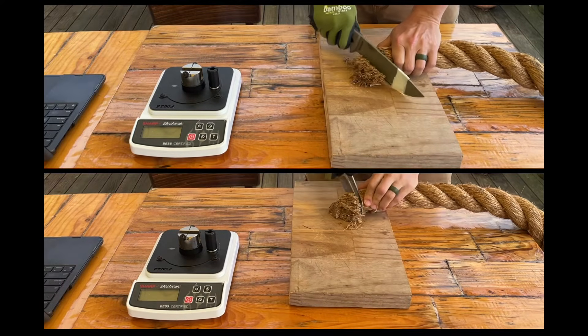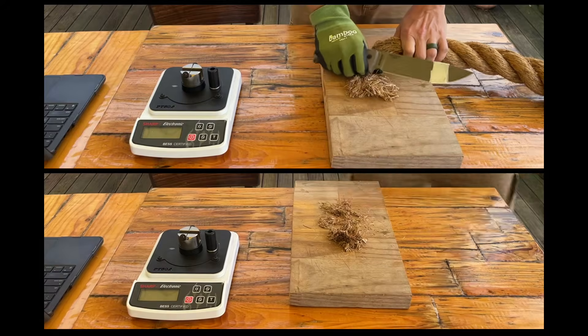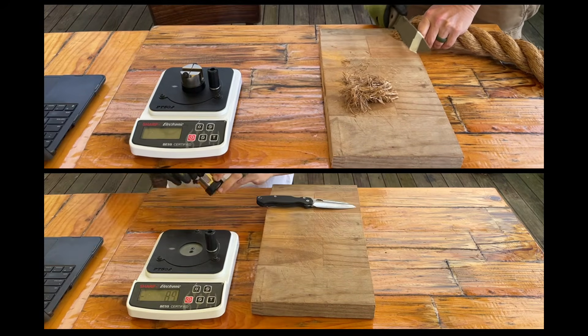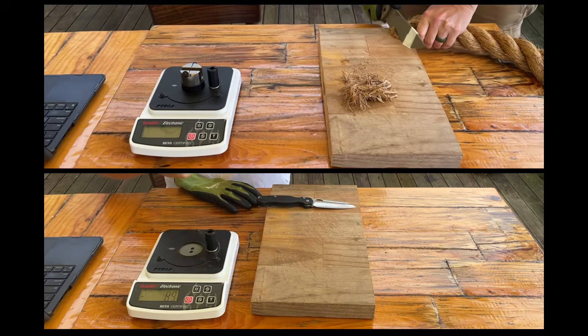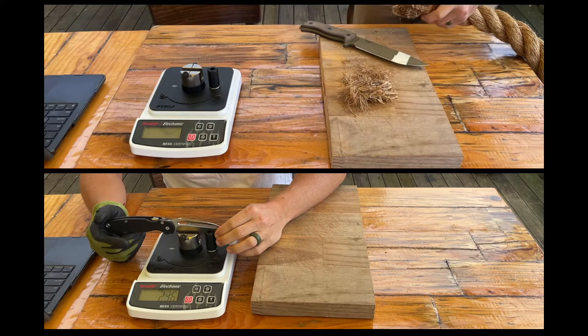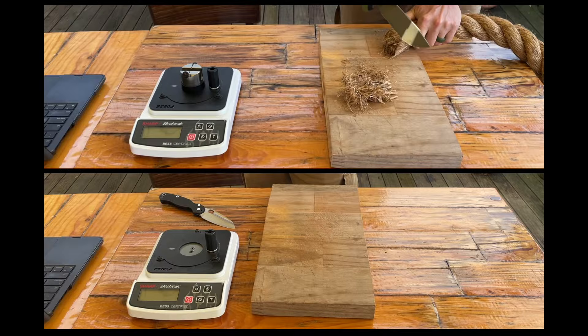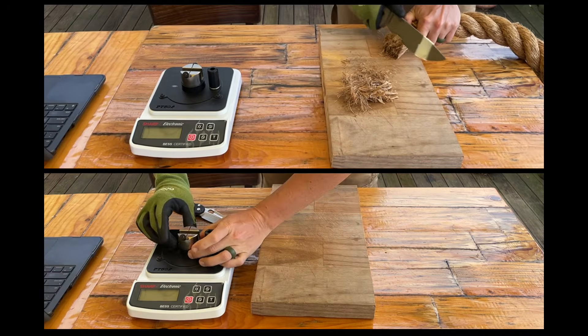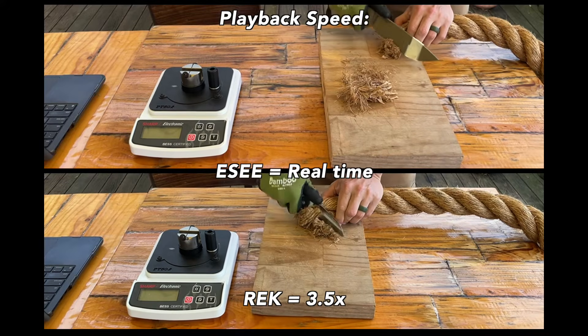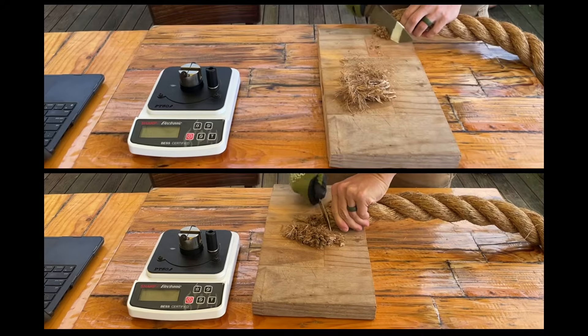The results are quite dramatic. The SE cut through the rope laboriously just one time — the first half felt amazing with that dual grit edge, but by the end I could not get through the fibers easily at all. It cut through the rope one time and tested over 400 grams on the best machine already, which is less than a Victorinox paring knife at around 57 Rockwell. I retested it in a different spot on the edge and it was indeed over 400 grams, so I became really curious what this custom rebladed 63 Rockwell 1095 was going to produce.